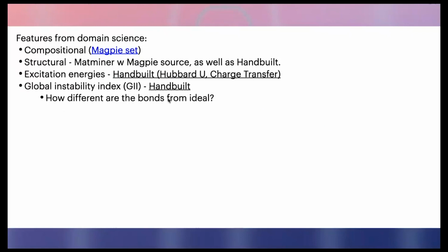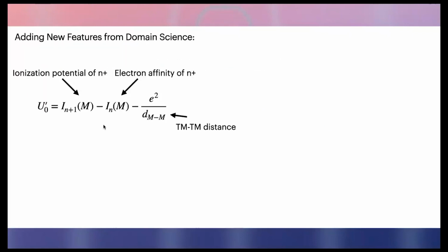Ideal is a sort of average over many materials. So obviously, we're not doing CRPA on the materials. It's not a very involved calculation, right? We get unscreened Hubbard U's, and that comes from an ionization potential, an affinity, and an electrostatic response, right? So you have a transition metal, what's the energy to move an electron from here to here with no screening and everything atomic energies.